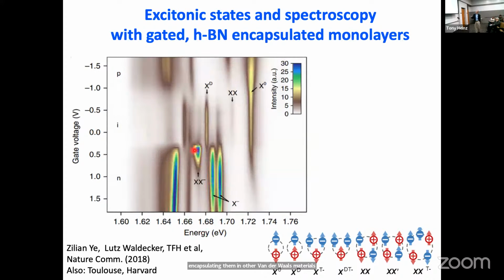So this is then an emission spectrum where the vertical axis is changing the charge density by gating, and the color scheme shows the different emission features. So we can actually see quite a few different things: a neutral exciton, these charged excitons that I mentioned, bi-exciton, charged bi-exciton. And also what's interesting is that the line width of the features is continuously decreasing, but it's actually getting to the fundamental radiative width.